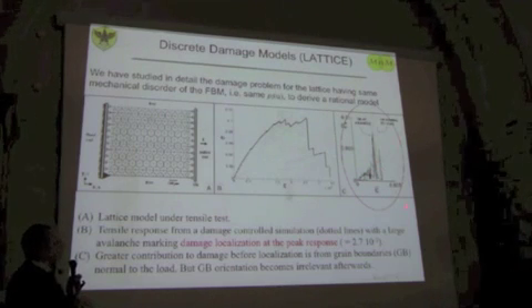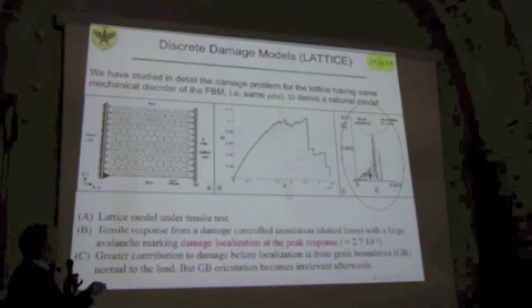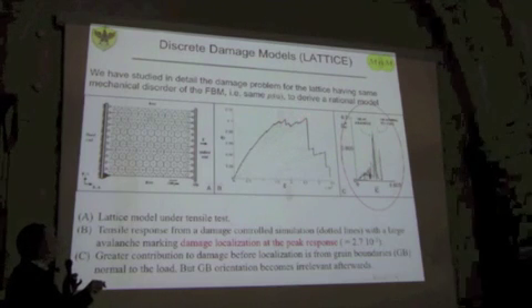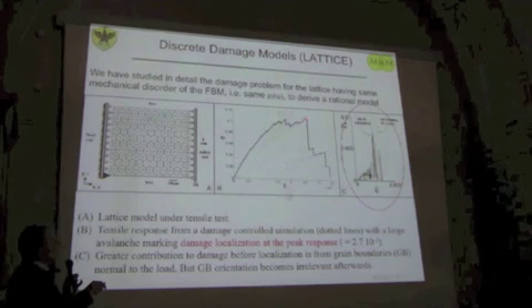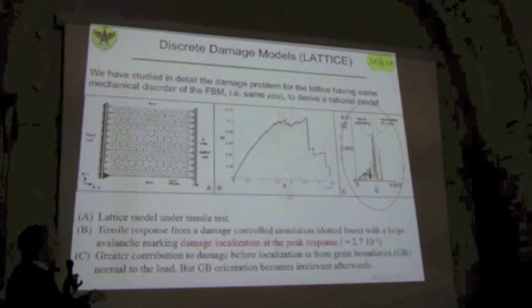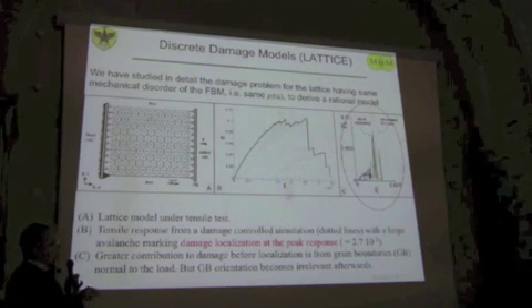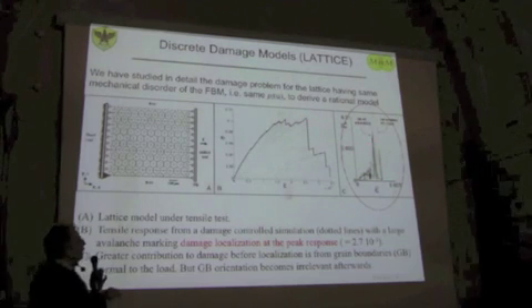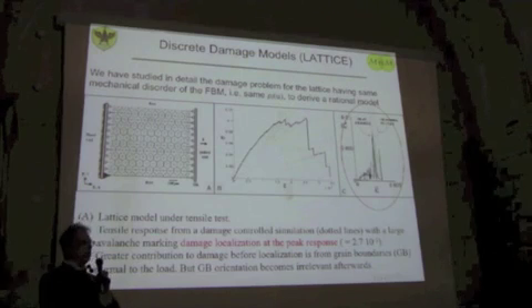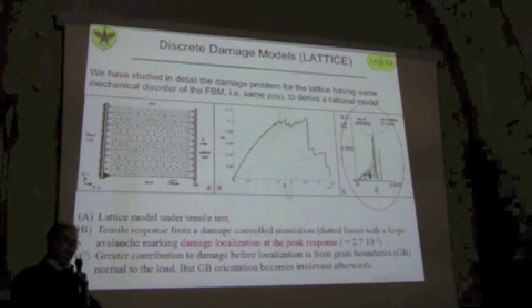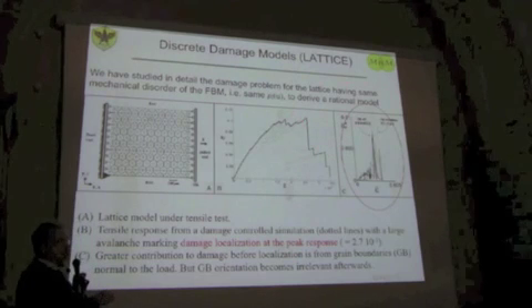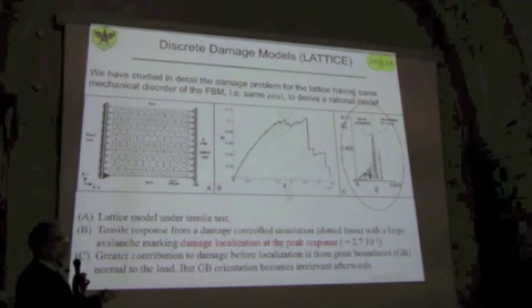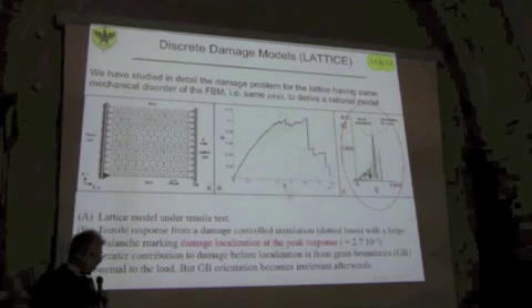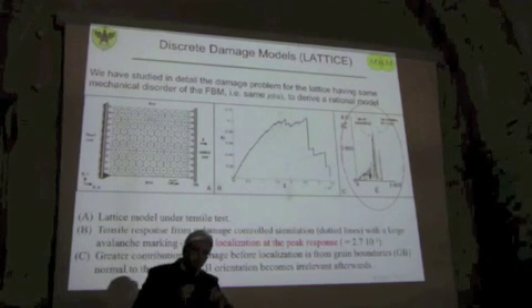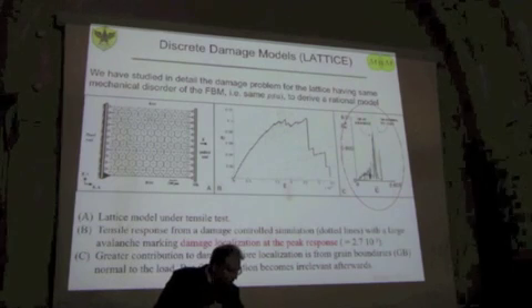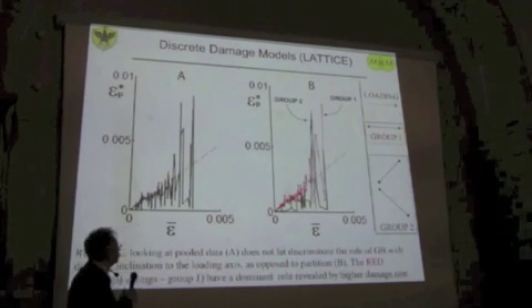Then something happens. There is an explosion. When I approach the peak of the stress response, you see an explosion, and what happens essentially, there is a damage localization, energy localization, and also springs that are very strong get broken, of course. There is an avalanche, and so the system experiences a transition from a homogeneous deformation to a localized deformation. So I'm just saying things that several of the previous speakers already brought into the picture.